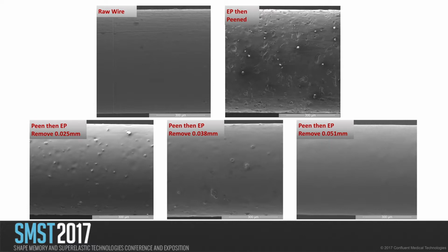We move over to the bottom center where we remove 0.038 millimeters of material, and you'll still see some areas of high contrast, but when we looked at them with EDAX, we didn't pick up any chemical trace from that peening media. When you look closer, you see that these are just artifacts from that media shielding the wire during the EP process, and then the contamination gets washed away. In the final lower right-hand corner, we have 0.051 millimeters of removal, and you see exactly what you want to see in any medical device, just a perfectly smooth surface. We saw no traces of contamination on that wire, obviously.